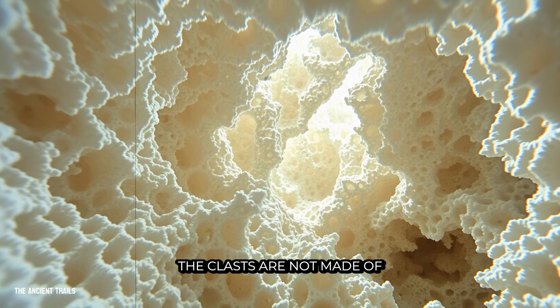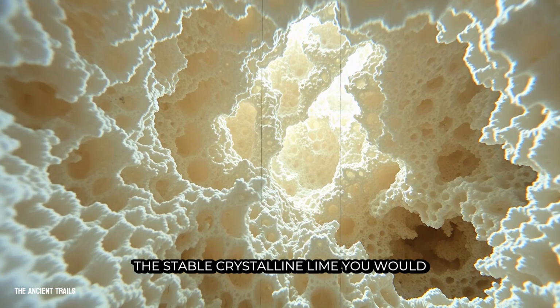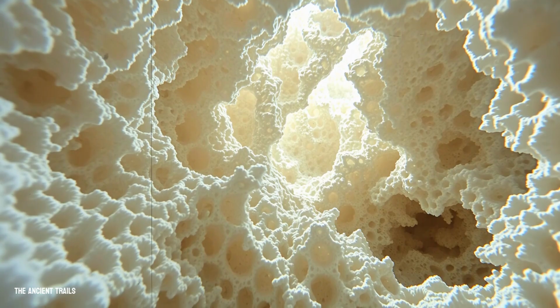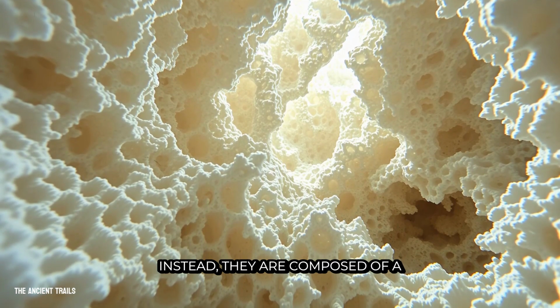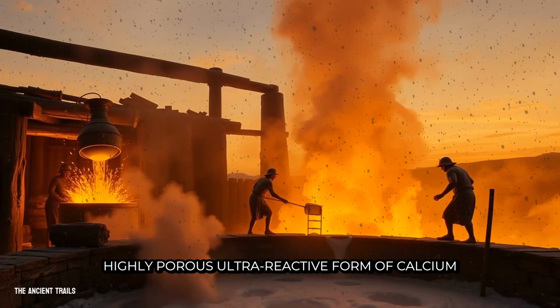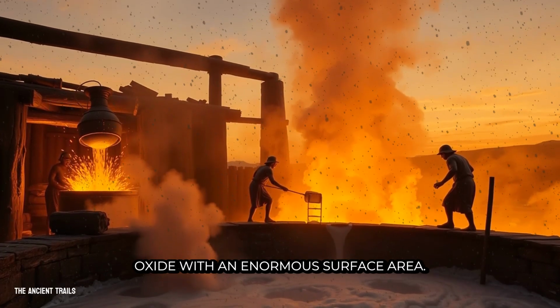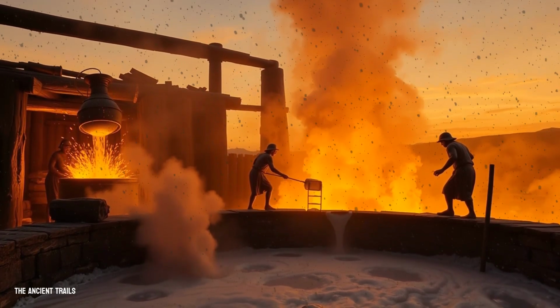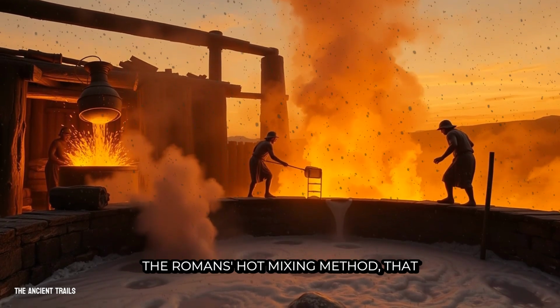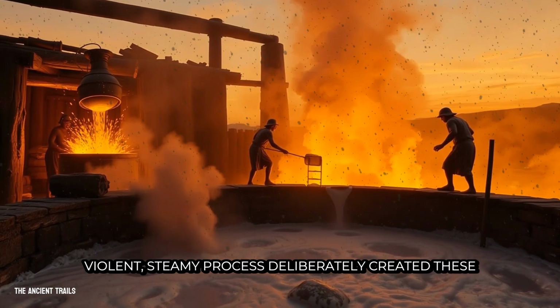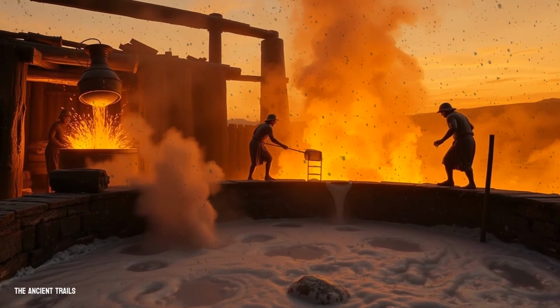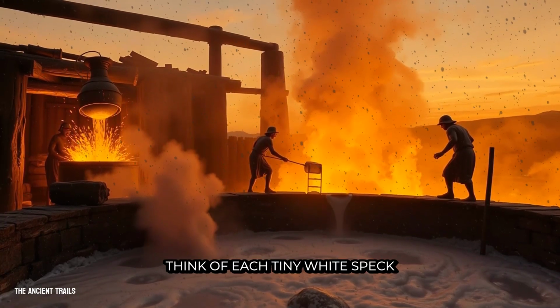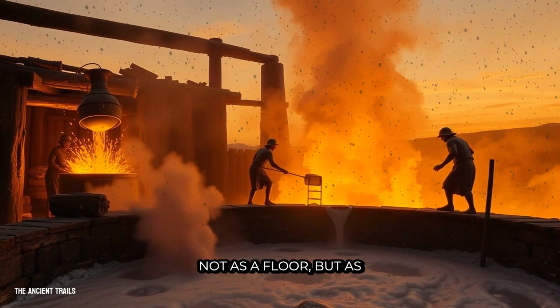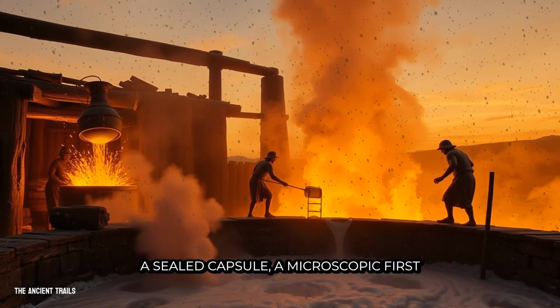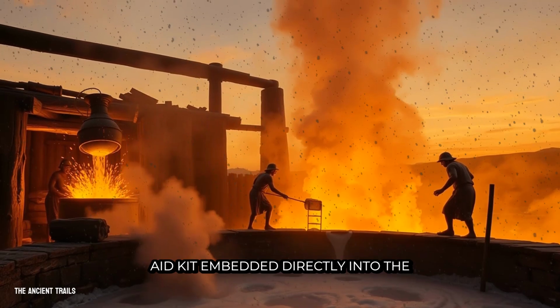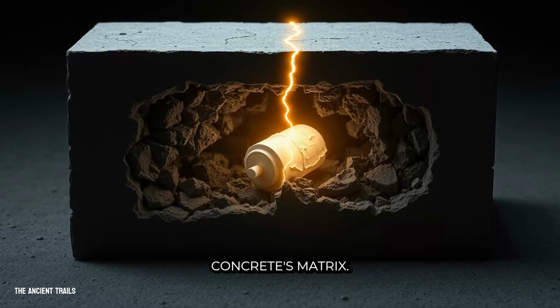The clasts are not made of the stable, crystalline lime you would expect from a slow, careful mix. Instead, they are composed of a highly porous, ultra-reactive form of calcium oxide with an enormous surface area. This was no accident. The Romans' hot mixing method, that violent, steamy process, deliberately created these nanoscale reservoirs. Think of each tiny white speck not as a flaw, but as a sealed capsule, a microscopic first aid kit embedded directly into the concrete's matrix.